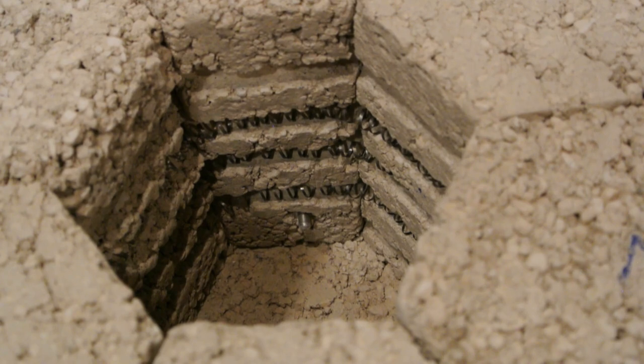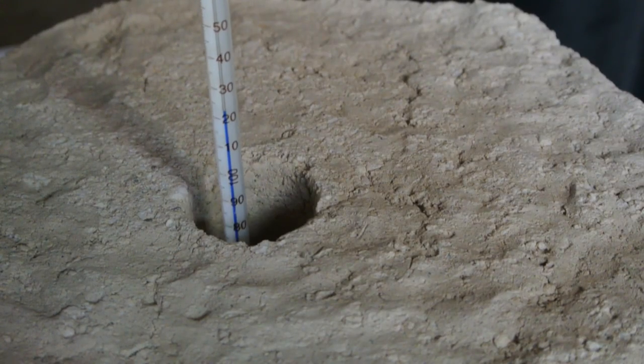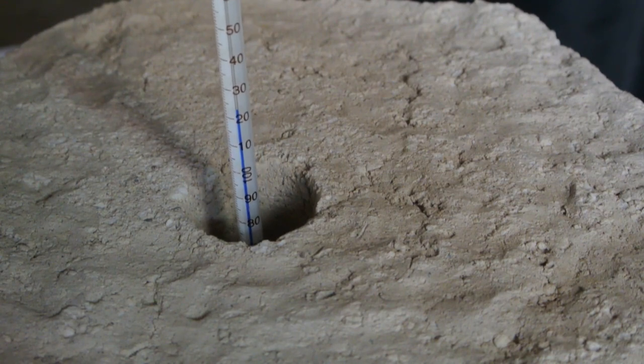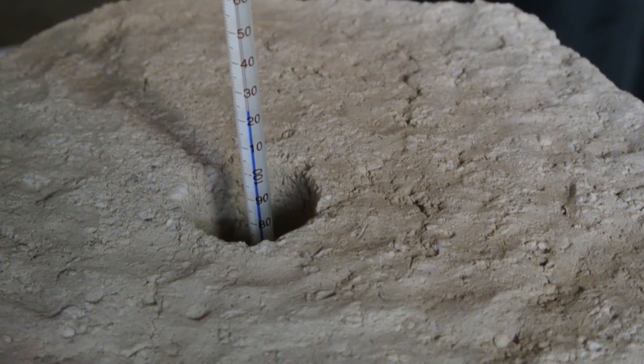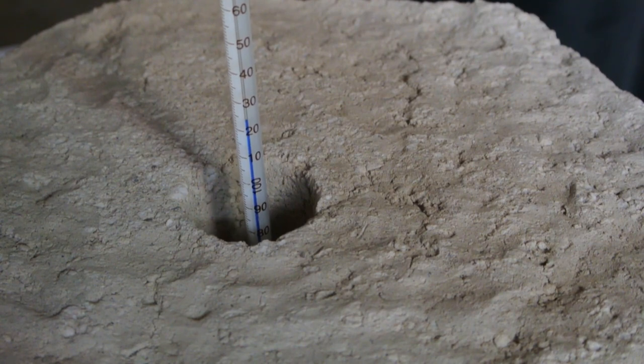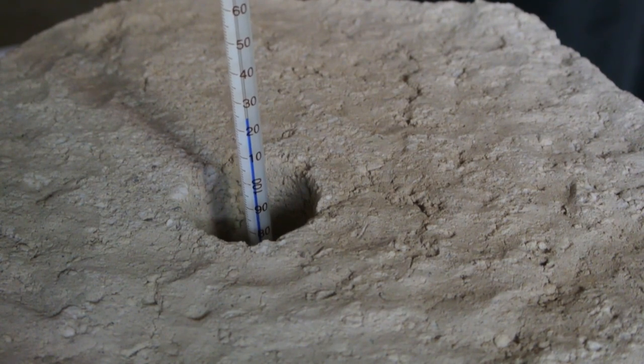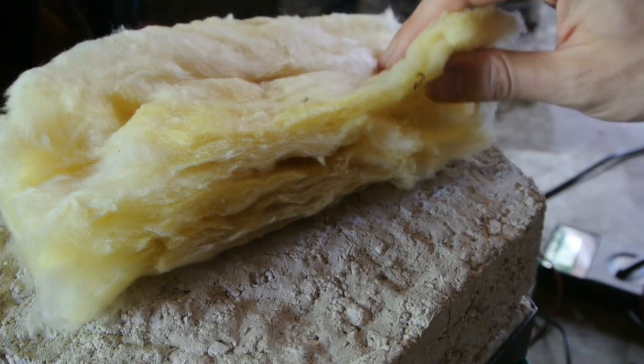For the first run of the furnace, I just hooked it up to a variac from an old gel electrophoresis power supply, and used a very low voltage to heat it slowly, driving off any water without cracking. Then, of course, I ran it at full blast, and it was awesome!